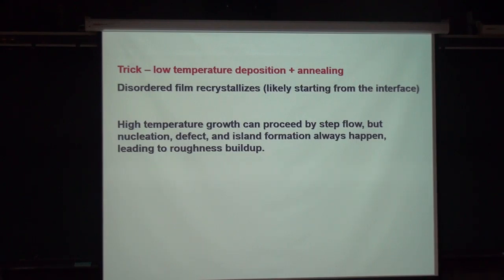But when the temperature is high, there's also an entropy effect, which tends to make things not so smooth. So the high temperature is important for the atoms to move around, but at the same time, it actually makes the film not so smooth. So we end up with a film which is pretty good, but never perfect. Okay. So that's MBE.